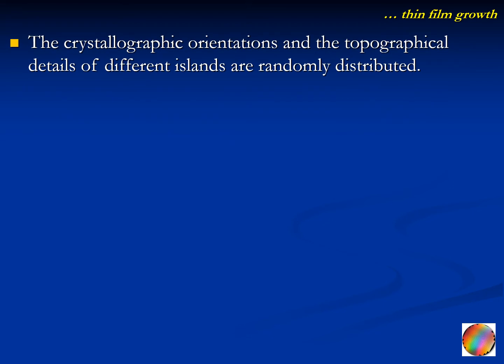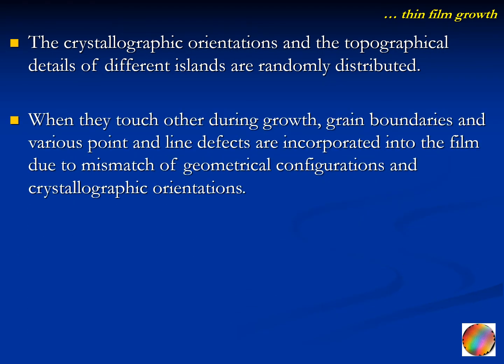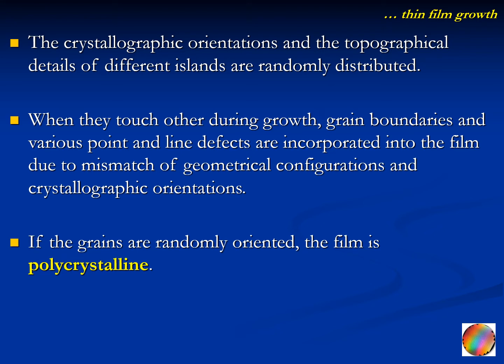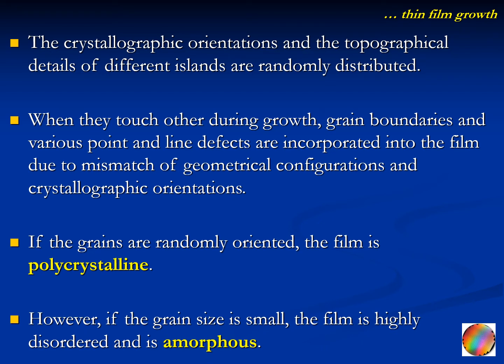The crystallographic orientations and the topographical details of different islands are randomly distributed. When they touch each other during growth, grain boundaries and various point and line defects are incorporated into the film due to mismatch of geometrical configurations and crystallographic orientations. If the grains are randomly oriented, the film is polycrystalline. However, if the grain size is small, the film is highly disordered and is amorphous.